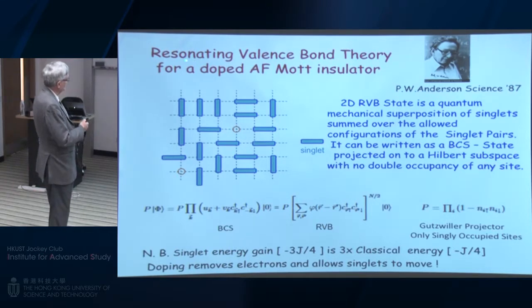idea that, in fact, this type of antiferromagnetic Mott insulator might still be on the verge of superconductivity if you doped it. And his argument was that if we consider this material as a quantum mechanical superposition of singlets, and we remember that a singlet for a pair of spins, of course, has a huge energy, which nowadays we would say is entanglement energy. It's 3/4 J, whereas the classical energy is only 1/4 J.